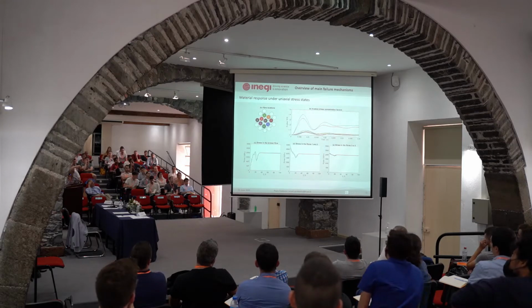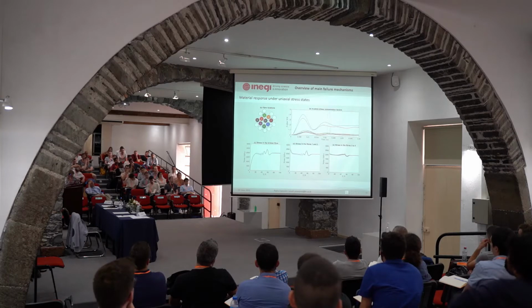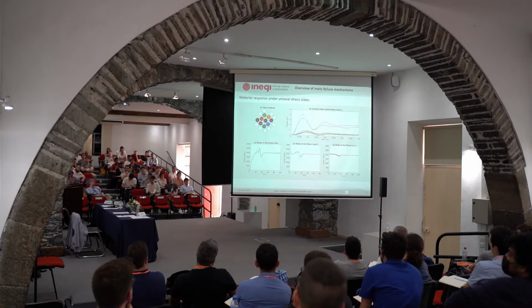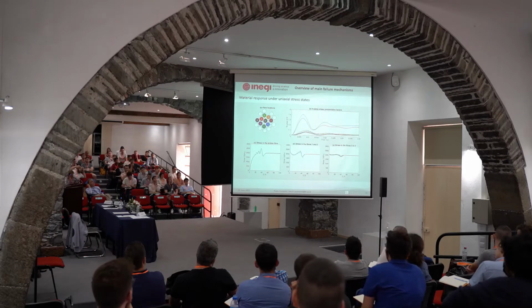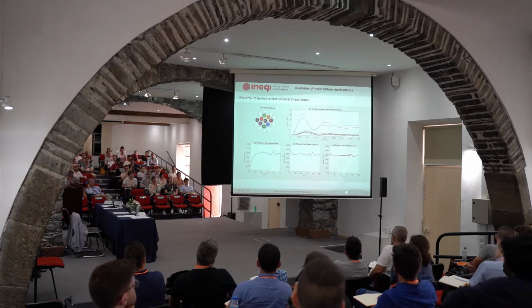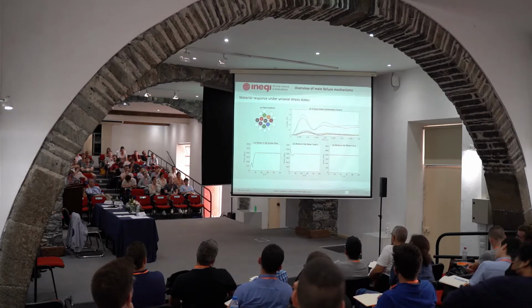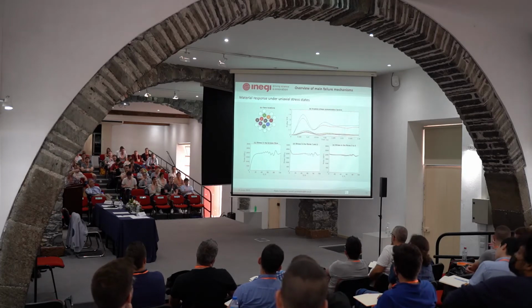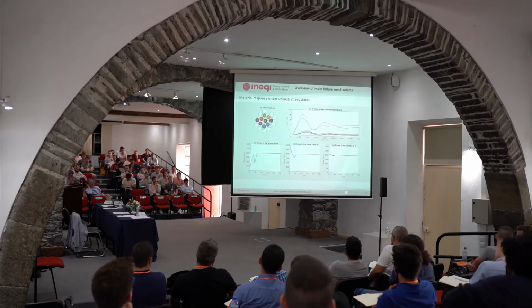And when this fiber breaks, you can see that we have this dynamic effect, okay? And this is important because most of the composite micromechanical representations of fiber fracture ignore this. So they are able to capture with good accuracy this stress concentration factor, but they completely miss this. Because of course you can imagine having a very stiff material under a tensile stress, and then it suddenly breaks, so you have all these stress waves that will propagate. So you can see that these two fibers, 1 and 2, are the ones that pick up most of the load, and the others are reloaded. So this is the stress on the broken fiber, and then in 1 and 2 as we move along in time. Okay, so this is again along the axis, so the direction perpendicular to the projection.